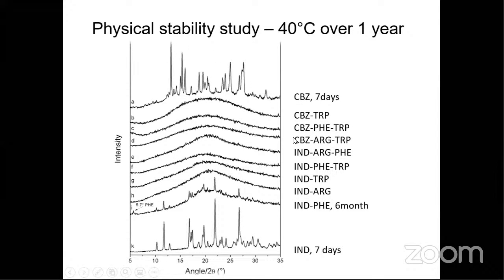For physical stability, we can see carbamazepine only stored for 7 days and they recrystallize very obviously. And indomethacin after 7 days also recrystallized. But for the coamorphous systems, except this one, all of the others remained amorphous. So basically it means the existence of the conformers can be used as a stabilizer to improve the physical stability of this pure amorphous compound.